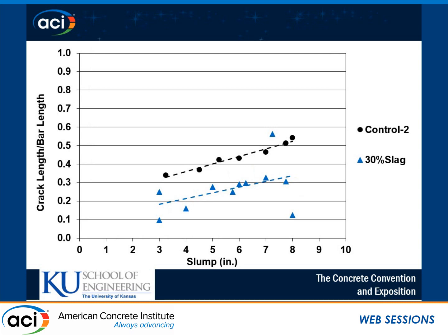We see a similar trend with our binary mix. So when we have our 30% slag mixture, we also see a reduction in settlement cracking. The mechanism behind that is that you're tying up more of that bleed water in the finer granules of that SCM.